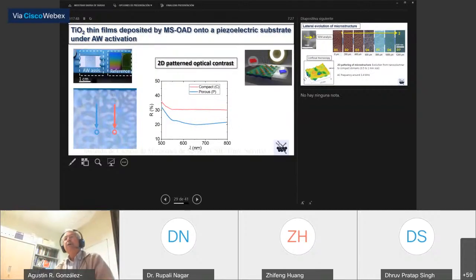However, if we make the experiment in an oblique angle configuration like this one in this schematic presentation, what we can see here is that there is a surface where we can see very clearly, even with the eyes, a 2D pattern of the structure. If we look in detail at the optical properties at this point or at this point, we can see that the reflectance is completely different. So we have domains with completely different optical properties.